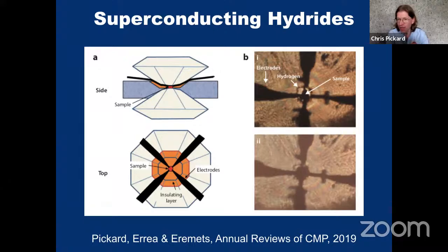I think they have to try it several times, and sometimes the leads will break, or sometimes the diamonds will break, and so on. But when they get it right, they get a result like you see on the right hand side, where initially you've got some initial sample and then some hydrogen, and you can see the hydrogen is transparent because it's insulating. The sample is not transparent, probably not insulating. And then as it's squeezed, the hydrogen disappears. So the hydrogen has gone into that sample to make a higher hydride that they then can go on and measure the transport properties of if it's metallic.